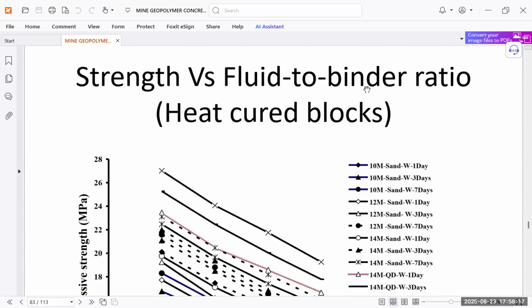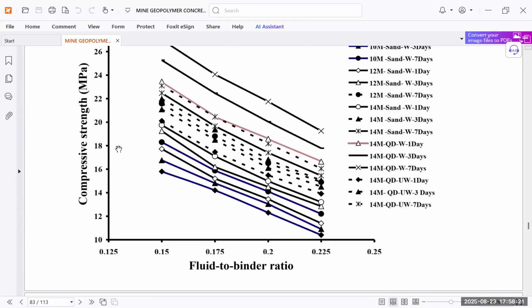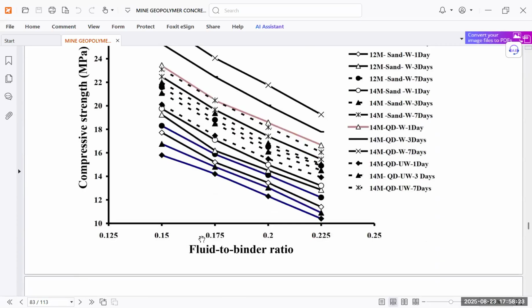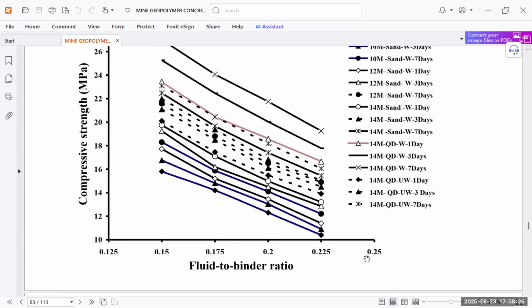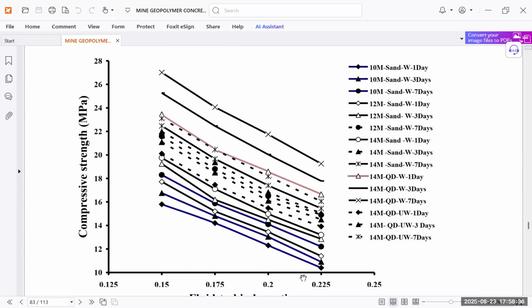We can see strength versus fluid to binder ratio. You can see this compressive strength. For the fluid to binder ratio, we have taken changes from 0.15 to 0.25. Okay. So these are the different fluid to binder ratios, and you can see the compressive strength is changing.